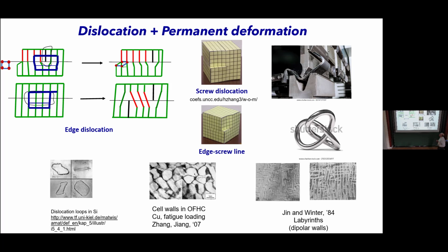So Philip introduced Burgers vectors to you. I'm not going to get into the details. For today's purpose, for my talk, it will suffice for you to think that dislocations are curves. They can run from boundary to boundary, or they can end in the boundary, or they have to be closed loops. From the pictures Philip showed, and even otherwise, wherever you have the dislocation curve, the lattice is messed up, and hence stresses are produced. And in 2D, these are 1 over R decay. More or less, at the core something will happen, it gets regularized, but it's 1 over R.